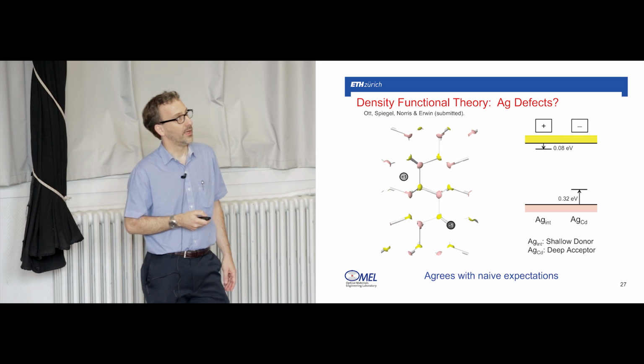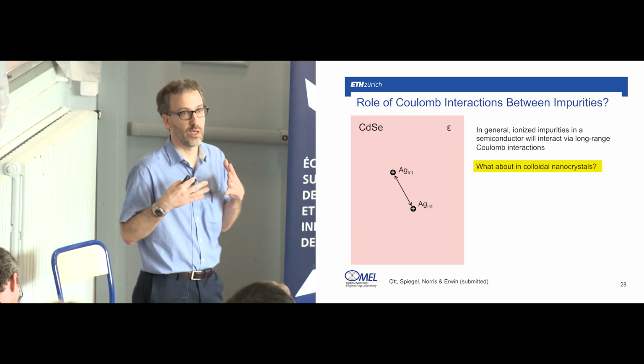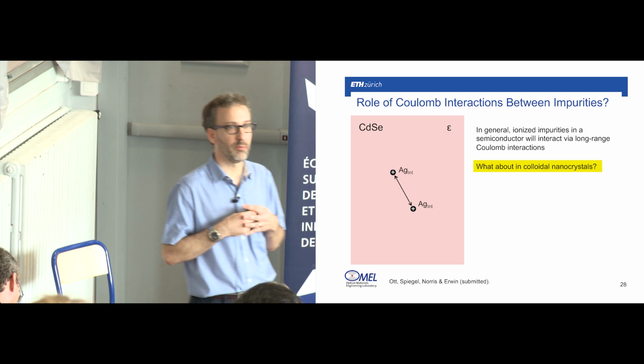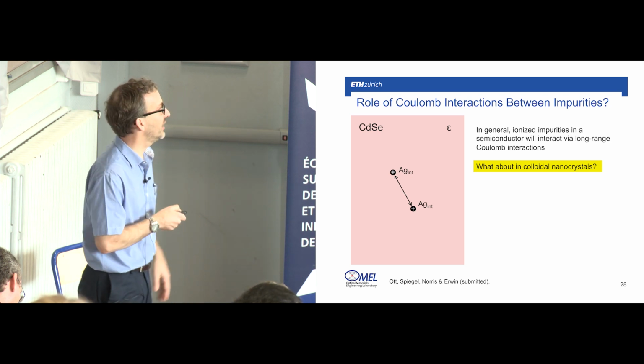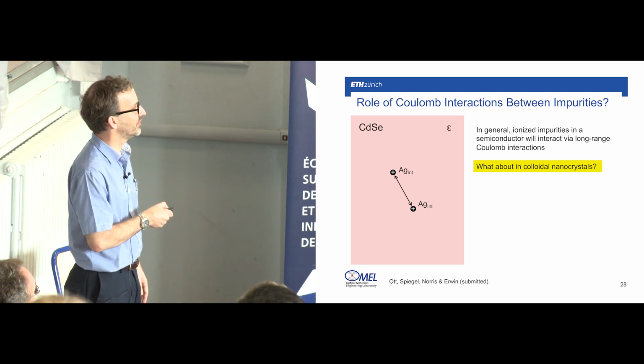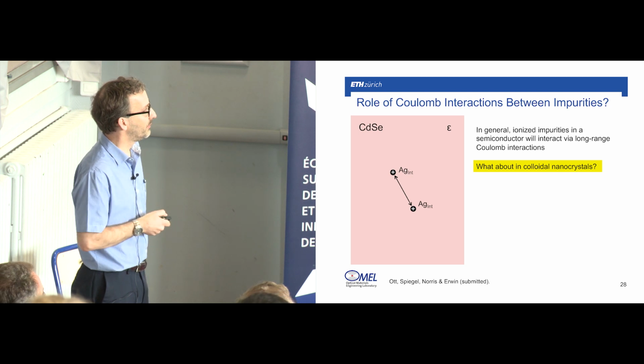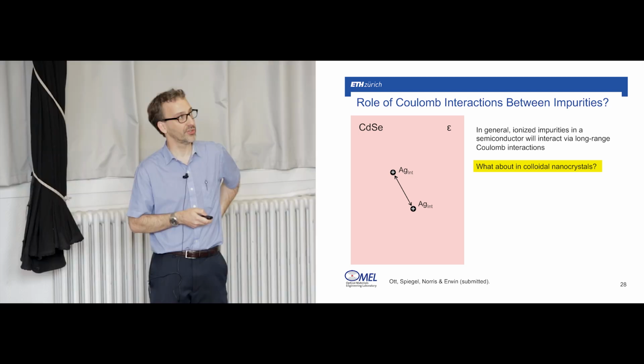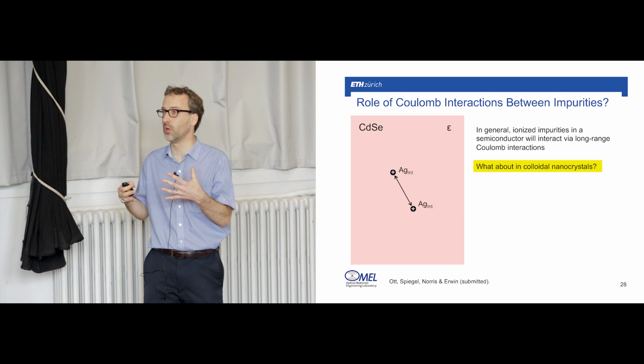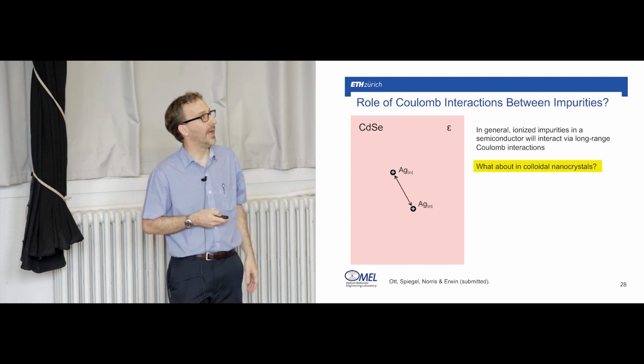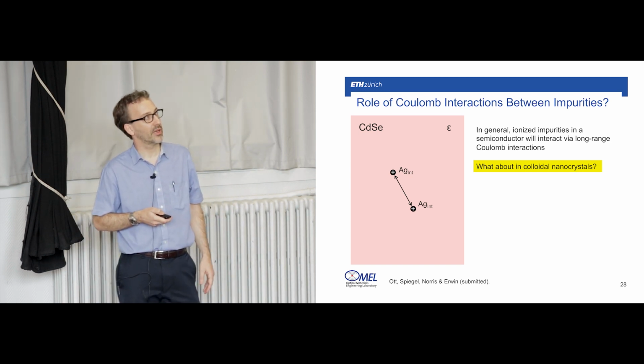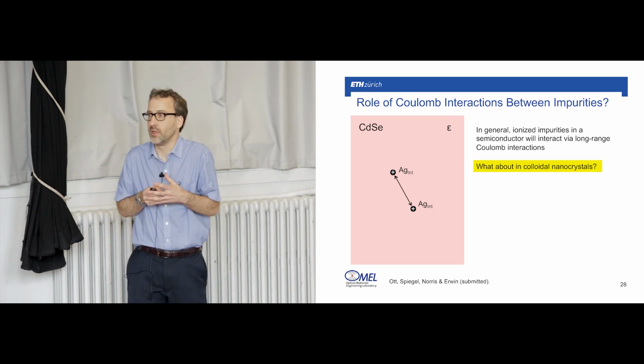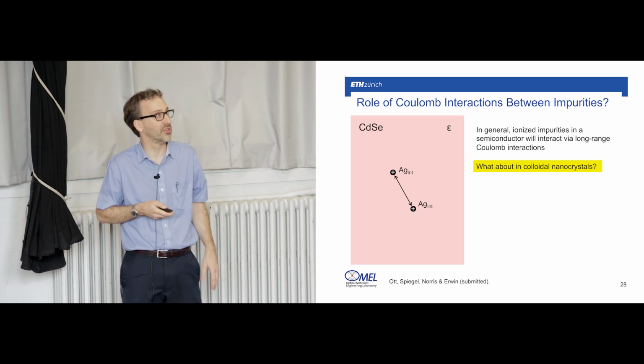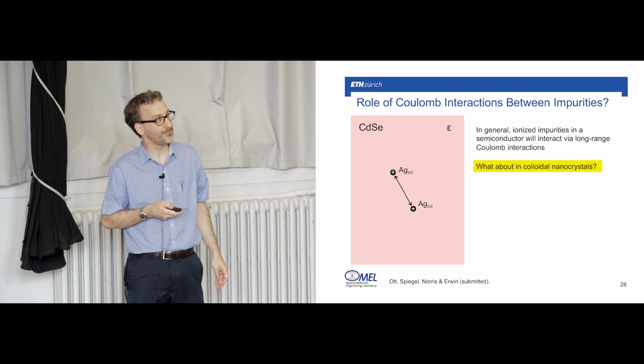Okay, now one thing that we didn't really appreciate at the beginning, but turns out to be everything in cation exchange, is if you now have ionized impurities. So let's say we have these two positively charged silver interstitials. Of course, they're going to interact by Coulomb interactions. And that would happen in the bulk, but of course we all know that if we now squeeze them inside a nanocrystal, these interactions are going to be even stronger.